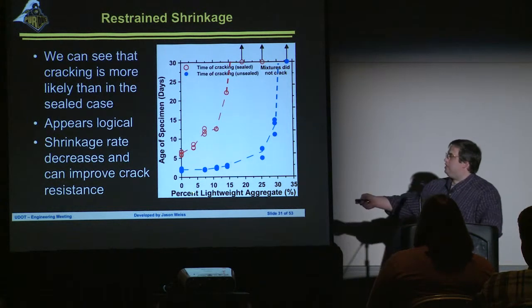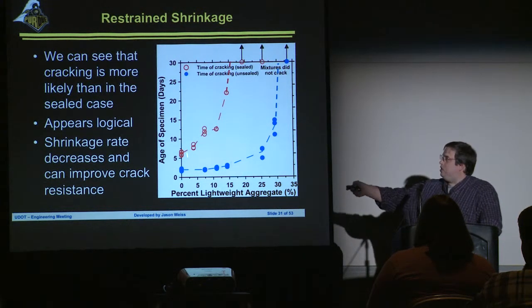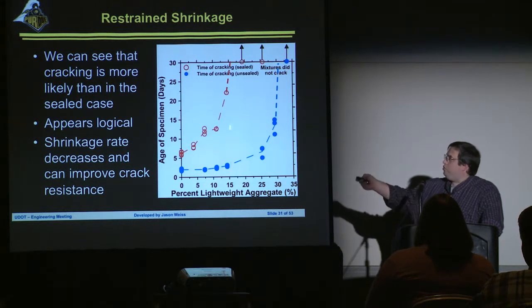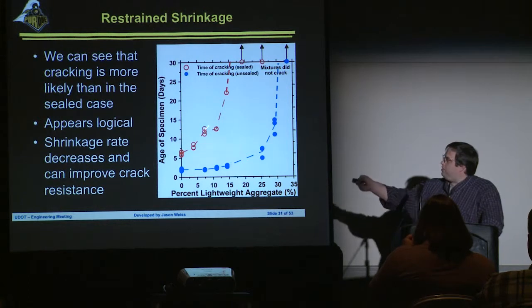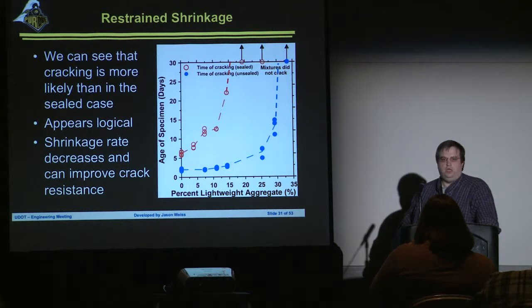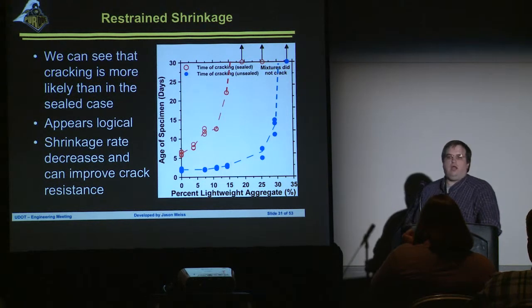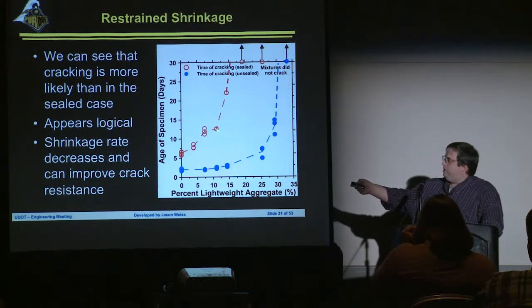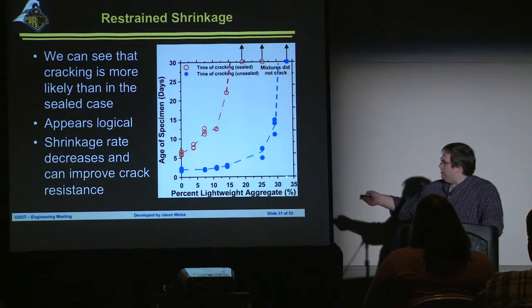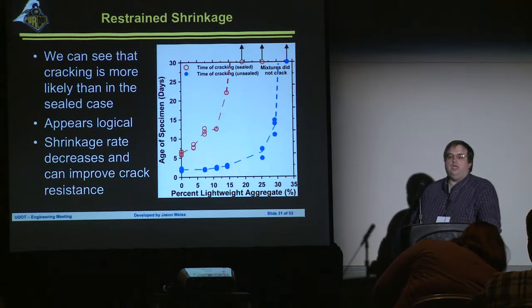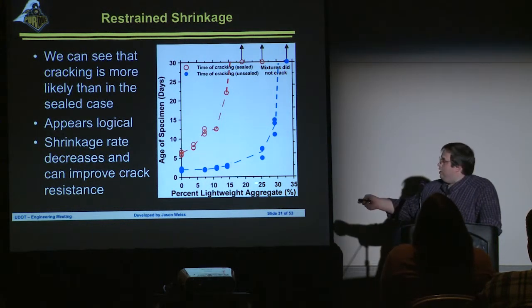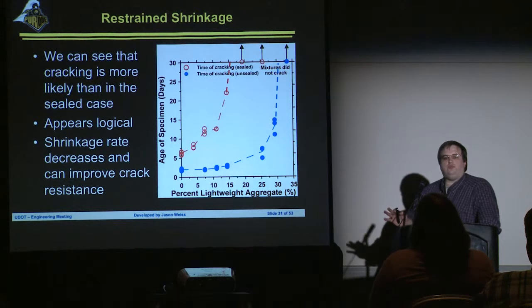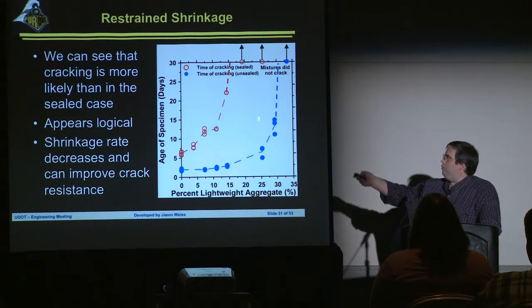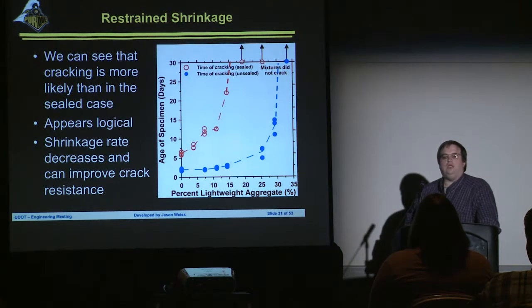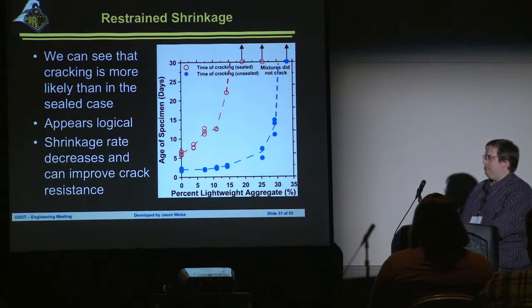And if we start to look at this, we can essentially see a plot of the lightweight aggregate along the x-axis versus the age of cracking. And what we can see is once we get to a critical amount of lightweight aggregate, this line starts to approach an asymptote, which essentially means that these mixes don't crack. If we have a system that undergoes both the sealed shrinkage and a drying shrinkage, we can see we need a little bit more lightweight aggregate, but again, we can get to a system that's not going to crack. We would have designed this mix just for self-desiccation to be at 23% lightweight aggregate. If we do that, we can keep the system from cracking. We've seen this over and over again when we do these different types of trials.